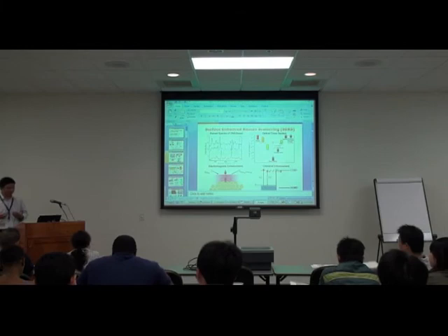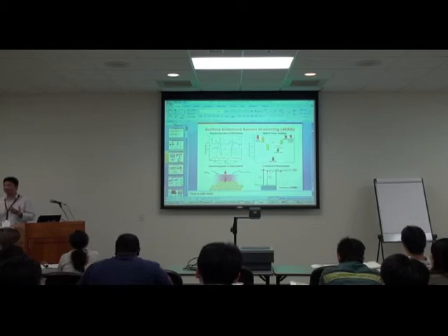Very good point. Of course, it depends on how well you design your system. If you have a good SERS substrate, the theoretical limit of electromagnetic enhancement is 8 orders of magnitude, 10 to the 8. And chemical enhancement is still under debate. Some people say it's 100 times, some say 1,000 times. So you have a 2 to 4 orders of magnitude range there. If you get the best such device in the world, you can get to 12 orders of magnitude. But in most cases, you end up with around 8 or 9 orders of magnitude.